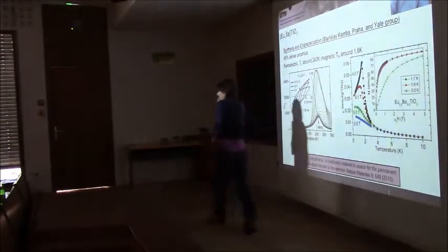But in the band with the europium, is it stable or not, at the thermal point, even if it's not too strong? So europium titanate, the bulk phonon band, when you calculate for cubic europium titanate, there's a very strong rotational instability, I think at the R point and maybe also at the X point. And there's a gamma point instability. I'm pretty sure there's a gamma point instability also from the cubic structure, but this goes away when you put in the rotations. Okay, yes. It's very close though, like strontium titanate, it's very close.